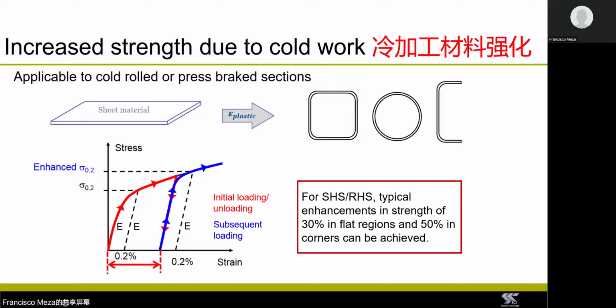Now, after the sheet is bent, the stress strain characteristic of the cold formed section will then be given by the blue curve. And this new stress strain curve will include an increase in the yield strength, some level of residual plastic strain, and also a reduction in ductility. Now, the reduction in ductility does not have a significant implication in design because the ductility of stainless steel is already more than enough.